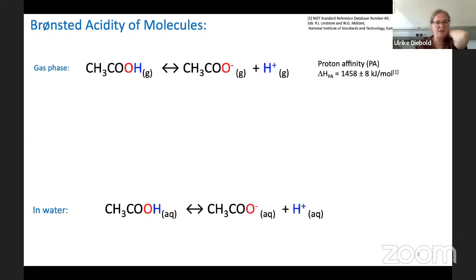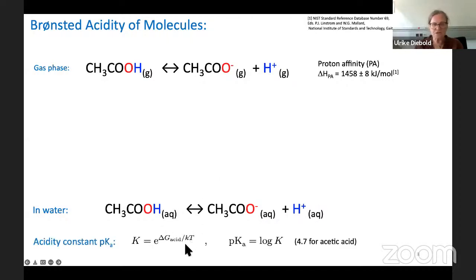So let me start with something very simple, the Bronsted acidity of molecules. So in water, what you have is, let's say, acetic acid, that's a weak acid, and in water you have some probability that this dissociates. The proton is dissolved in the water, and then you can measure the acidity constant here, and then depending on the change in Gibbs free energy, this rate constant will be faster or slower, depending on the temperature, of course, and the logarithm will give you the pKa, which for acetic acid happens to be 4.7.